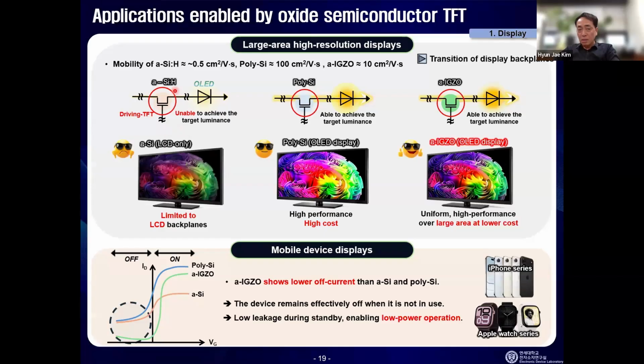But for LCD, they use amorphous silicon. This is very easy and cheap to make, but there is a limitation of the performance as a transistor. So only for LCD, okay? But nowadays, many people use OLED for mobile and even TV. They use polysilicon. This is much better than amorphous silicon. Like, look at this, 200 times higher, faster, the mobility. But still, this oxide semiconductor is amorphous phase, still like 20 times bigger, higher.